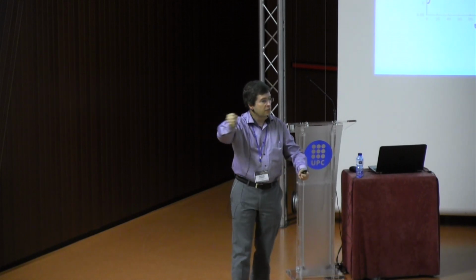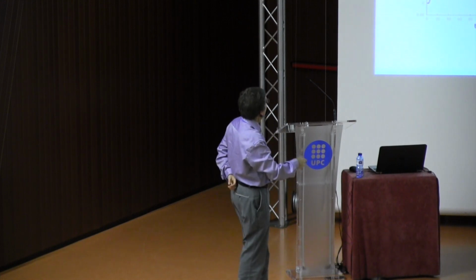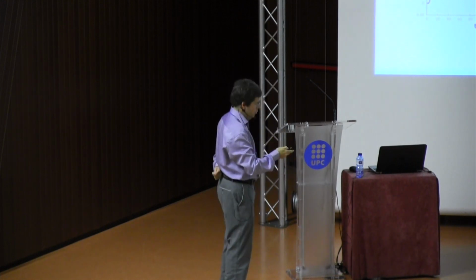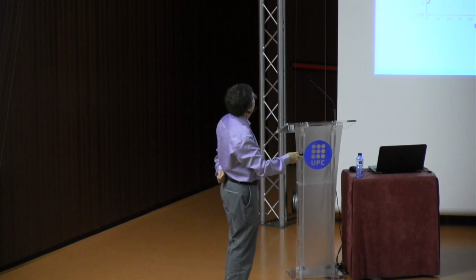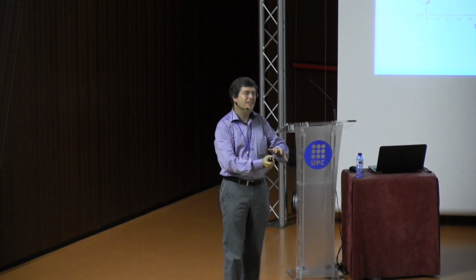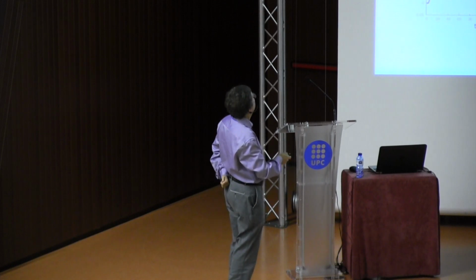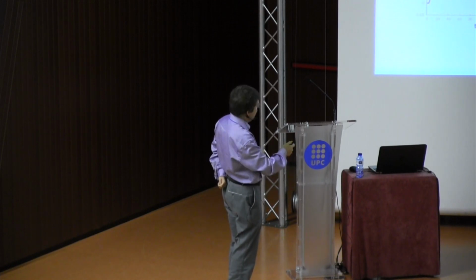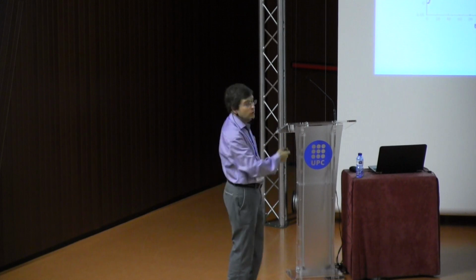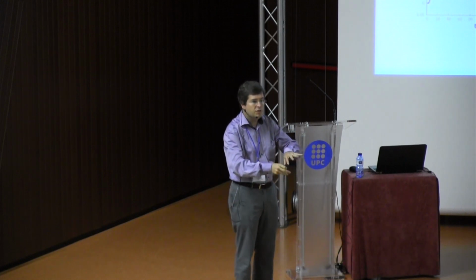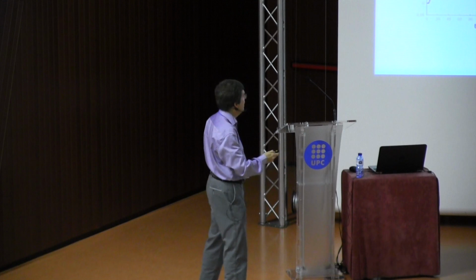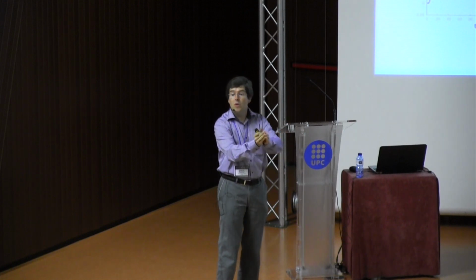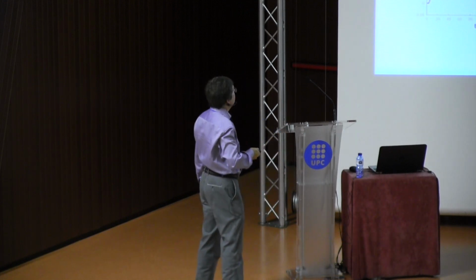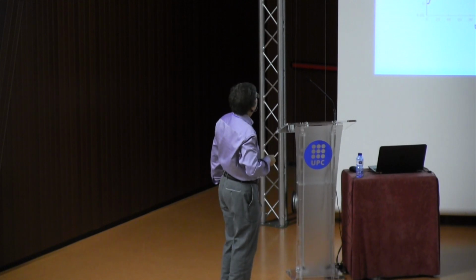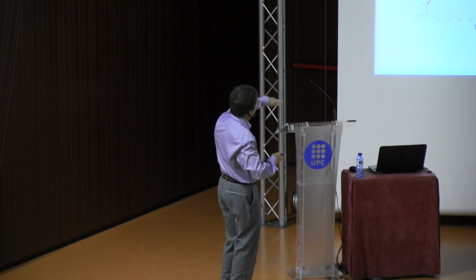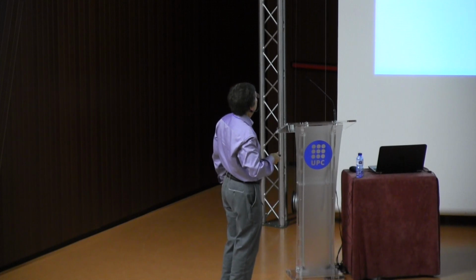In fact, you should have no forces. So this you can check in the model by the other forces, and so on the other side. And then you come back, and then you can compress it to close the crack. Let's close the crack like this. So we come back here, and then we can go again into the elastic regime. So this is coded in the damage model that we have here on each of the 111 planes. So let's use it. Now elasticity here, and even plasticity if you have too much compression.